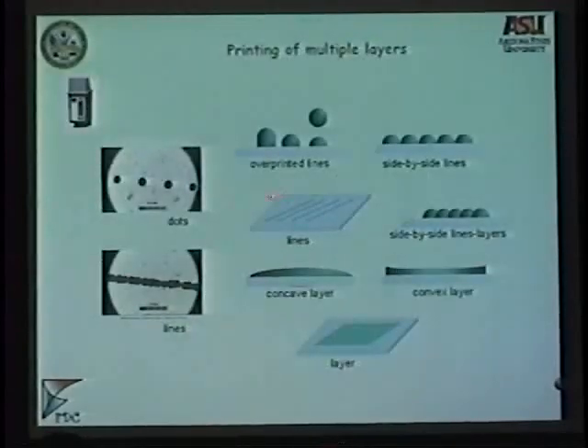So by using that system I talked about, we can print dots, we can print lines, and we can print layers. We can adjust the chemistry of the ink and get either concave layers or convex layers or any other shapes that the ink chemistry would allow us. And this has a ramification in solar cells as well as in light extraction.